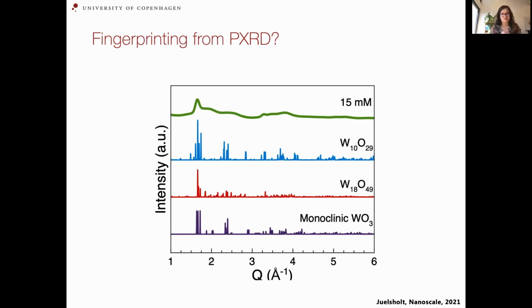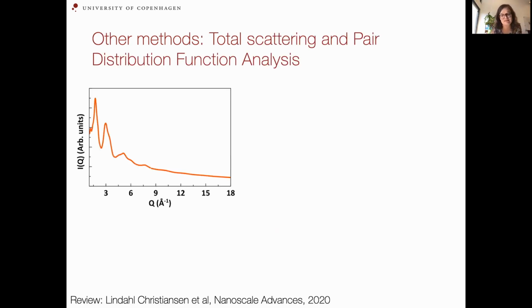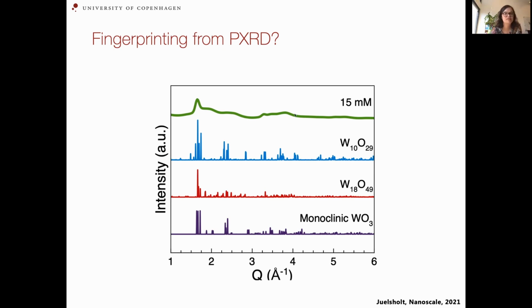If we did it the conventional way, we would just compare our data to reference compounds, so to calculated PXRD patterns from different structures. And you can see it's really difficult to make this fingerprint, as we can usually do for crystalline materials, because we just have really broad peaks, and all of these materials actually have somewhat of a peak where we see this. So we go to a different method. We use what we call total scattering and PDF analysis, because as you can see, there is information in this scattering pattern. It's just about getting it out beyond the Bragg peaks.